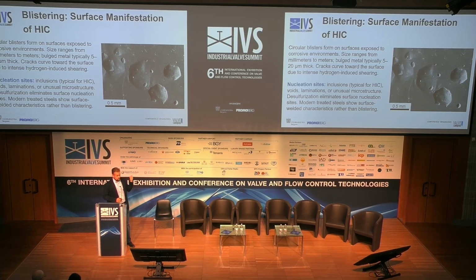How do we prevent the formation of this one? This is actually very observable on high pressure vessels. Usually the sulfuric groups on top of metal, which in most cases are just contaminants, act as nucleation sites. So you're having nucleation sites which induce the formation of the blisters. We noticed that by desulfuring the metal, we drastically decreased the formation of the blisters. So it's just a matter of working with a specific standard, and given that this kind of event can lead to the failure of the vessel, it's something very important. So people are starting to get much more sensitive also regarding good manufacturing procedures in terms of the formation of not only pipelines but also pressurized vessels.